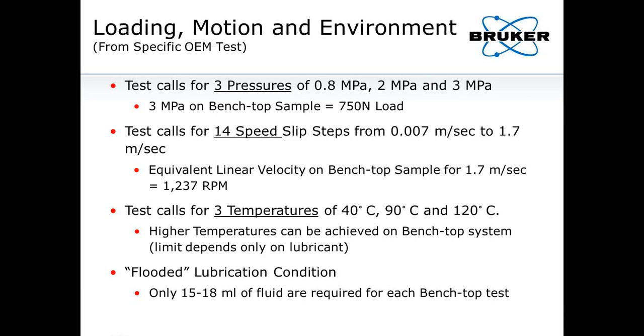This same OEM test calls for three different temperatures — 40, 90, and 120 degrees C — and we can do up to that and beyond; our limit really depends on the lubricant. We can go to 400°C but ATFs typically max out around 160–180°C. For the environment, we use flooded lubrication conditions — we always want lubricant present. In the benchtop test, this requires only 15 to 18 milliliters of fluid, which is quite small.